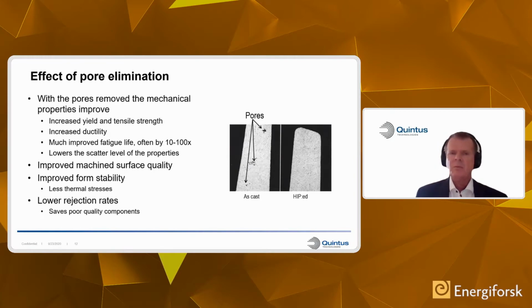And with using hot isostatic pressing, you are able to remove these pores, which will then have an effect on the mechanical properties, as I mentioned. And I would say the fatigue life is probably the dominant property that will be affected. We've seen that it can be extended by 10 to 100 times.